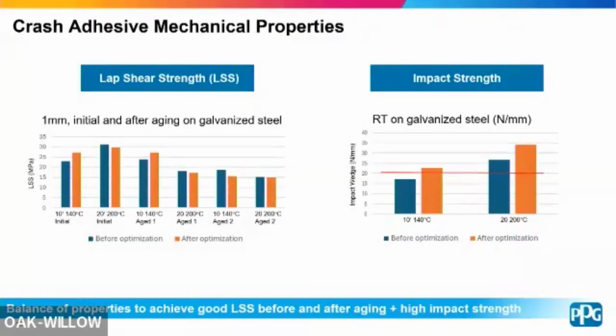And then we looked at a couple of different aging experiments, and without going into too much detail, it's essentially humidity and heat aging cycling. Aged 1 would be after cure, and aged 2 would be looking at heat and humidity exposure both before and after cure, so much more aggressive test. And you see a little bit of trade-offs in that performance as well, but within the noise, I think, and we get good improvement at that, especially at that 140C after optimization for that first aging condition.